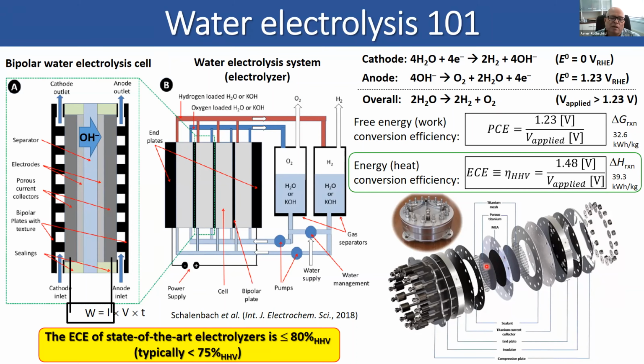So I call this coupled water splitting, because in this conventional technology, the oxygen evolution reaction that occurs at the anode and the hydrogen evolution reaction occurring at the cathode occur simultaneously in the same cell, and you must use a membrane to separate the gases, and you must use sealing in order to prevent the mixture through the system. So these are the major problems we have that essentially translate into high hydrogen production cost,